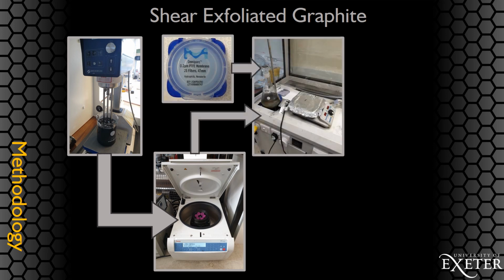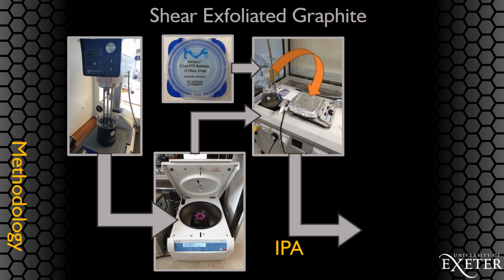The new SEG solution is filtered over a Buchner funnel and Teflon membrane, eventually leaving a dark disc of shear exfoliated graphite. The membrane is carefully transferred over a warm hot plate containing the substrate and placed face down after several sprays of isopropyl alcohol.